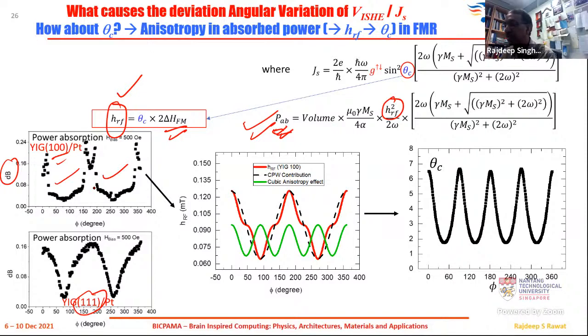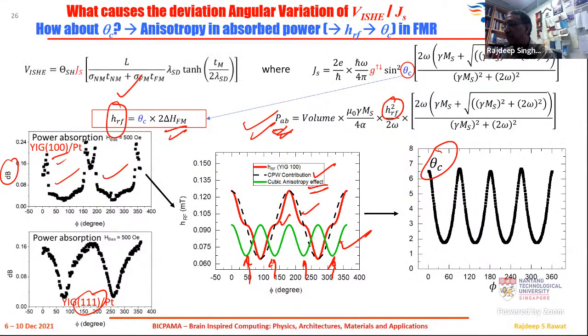Actually, it was mimicking something like the variation in the ISHE. So if you fine tune it a little bit, or basically try to remove too much noise, this is what the red curve is trying to show. And this again can be fitted with two functions, one with the CPW contribution, which is again the sinusoidal function, the black curve, and then the effect of the cubic anisotropy, which again is the fourfold anisotropy, which is seen over here. And if you use this cubic anisotropy contribution and divide it by the curve of the delta H, which was in the previous slide, you can find out that this precession cone angle shows a very strong cubic anisotropy dependence. So that basically explains what is happening in our system.